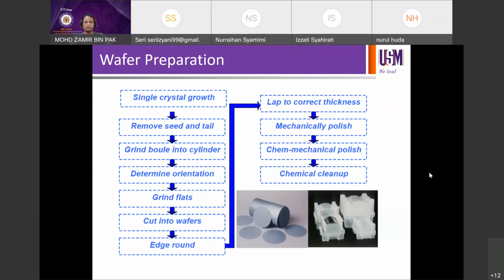We discussed crystal growth in our last lecture, then the removal of seed and tail from the ingot, right? Grinding of the ingot into a cylinder, and then marking the orientation, rather than determining it, because we've already determined the crystal orientation during the growth process. Marking the orientation according to the flats and notch, and we grind the flats to mark whether it is P type or N type, 100 or 111, and so on.